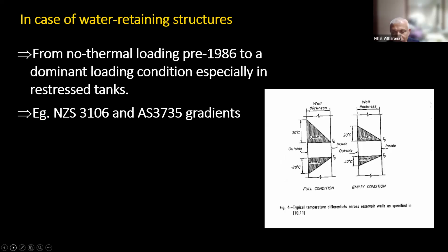Now, this is unlike any other standard in the world. In the New Zealand and Australian standard, we give this temperature distribution, which needs to be satisfied by the engineers as a minimum. Our standards are not legally binding, so the engineers have their own duty of care, but they say this is a minimum against which you need to design your structures. What you can see on the left is tank full and on the right is tank empty. When the tank is full, in the summer, the external temperature can go up by 30 centigrade compared with the internal. In the winter, like in New Zealand, it can go down to minus 20, while inside is at the water temperature. When the tank is empty, it's not that severe because the inside of the tank is getting heated up too, so the differential is much less.